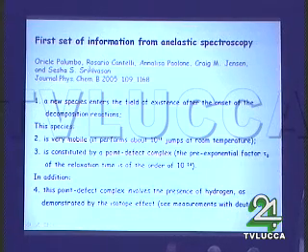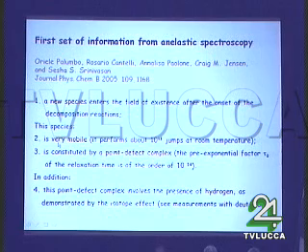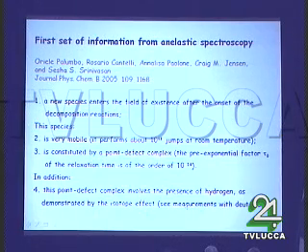So what information did we get from this first set of experiments? A new species enters the field of existence after the onset of decomposition reactions. This species is very mobile, is constituted by a point defect complex, and this point defect complex is hydrogen, as confirmed by the isotope measurements.